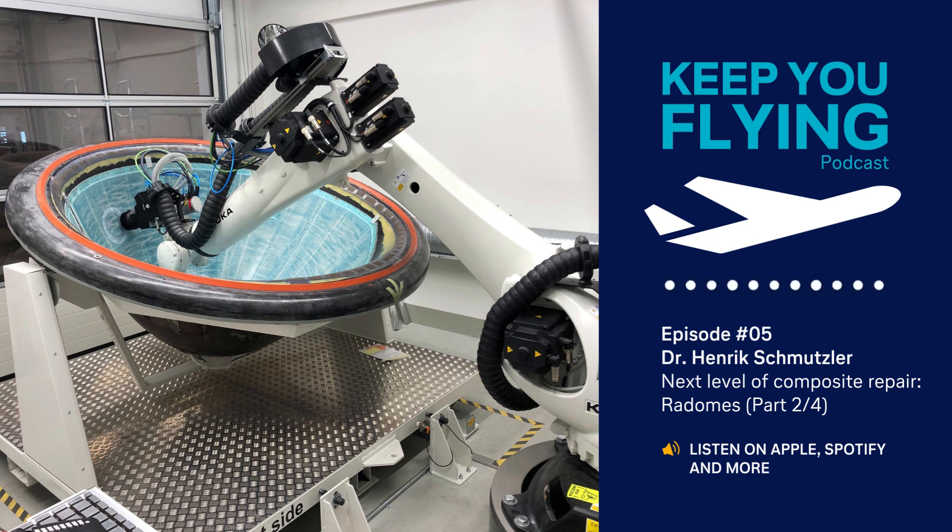When it comes to a short and medium-haul workhorse like the Airbus A320 family, the spectrum of causes for radome damage is varied. In daily operations, it ranges from bird strikes and excessive hail and lightning to water ingress. What all these causes have in common is that they usually affect rather large areas, causing delaminations and/or disbonds in the composite material structure. Standard repair processes described in every component maintenance manual usually require a lot of manual labor and are very time-consuming. For maintenance crews, the manual process also causes excessive stress, as the geometry of nose radomes often mandates some rather unergonomic working positions — the radome is placed on a trestle and the worker sits underneath, grinding above his head or within a constricted room.